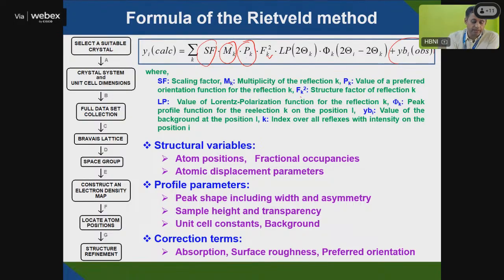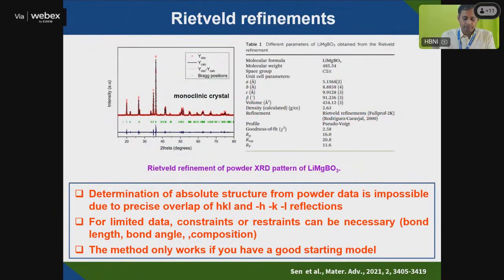First you have to take a suitable crystal model from the software, then the crystal system and unit cell dimensions that you obtain from your XRD, which you provide. You insert the database, then mention the Bravais lattice and space group, and once you get the constants, you will finally get the refinement. And you can see an example here: this is the monoclinic crystal structure of lithium magnesium borate. You can see the red one is Y observed, Y calculated is the line here, and this is Y observed minus Y calculated.